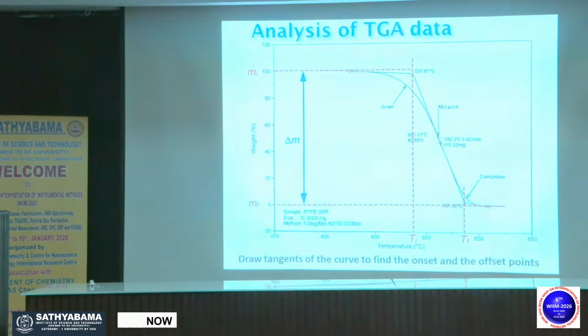So it's simple, no? It took less than 1 hour. So 1 thermogram, how much information it is giving? Is sample pure? Because nothing is degrading. Is it a mixture? No. It's one component. How I know? Because I see only one hump. Is it pure? Yes. Because there is no noise.